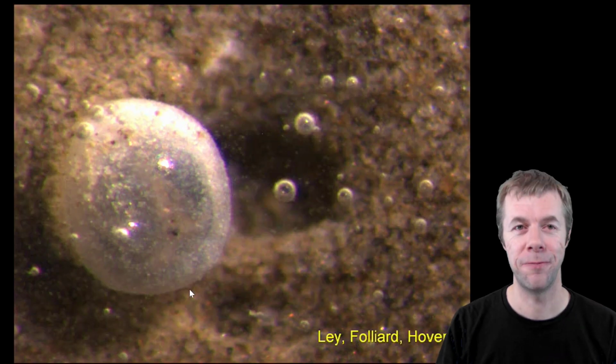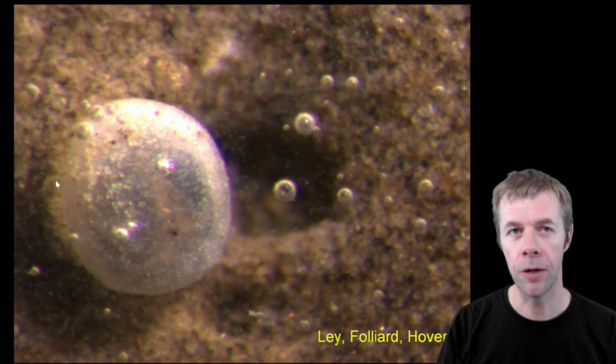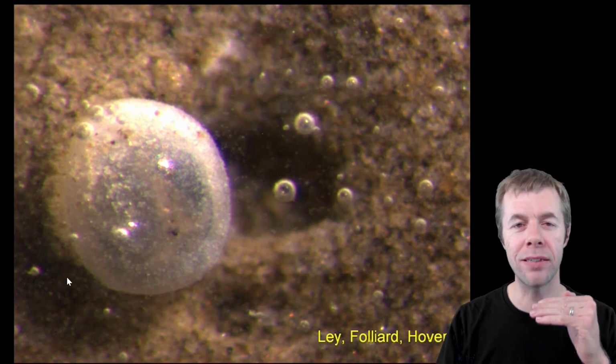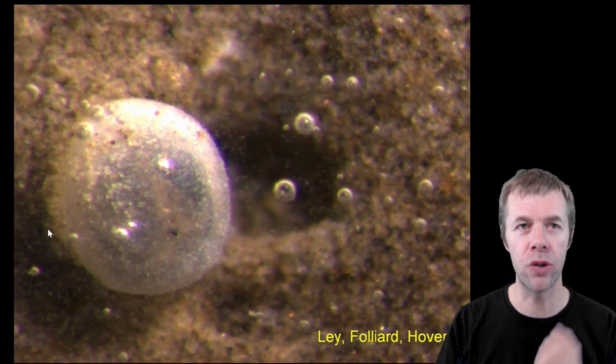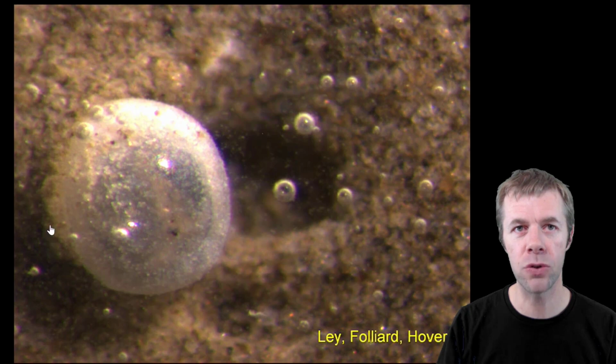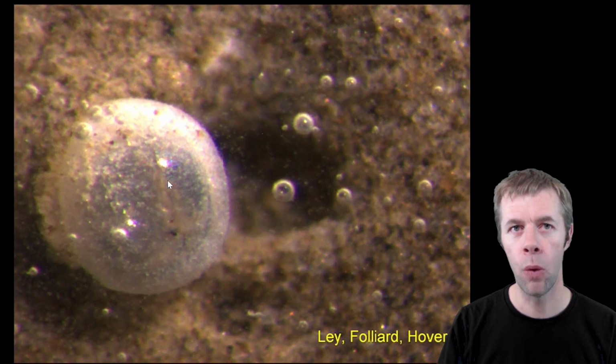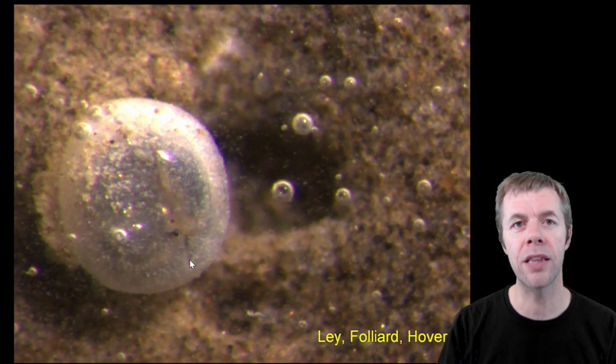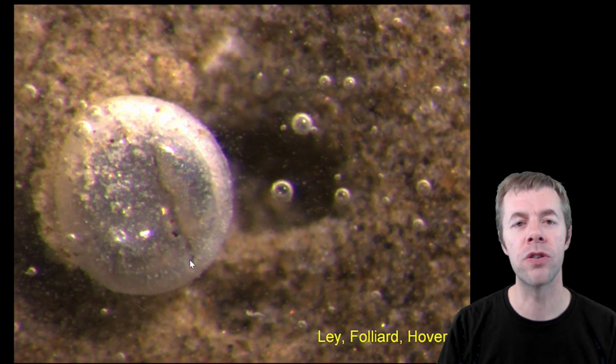Let's watch it again. I want you to keep your eyes down here. What happens is the cement paste is expanding because it's heating up while it hydrates. As it expands, you'll see it impacts or pushes. And once it starts to push, watch, there'll be a crack that forms right in the surface of the bubble.